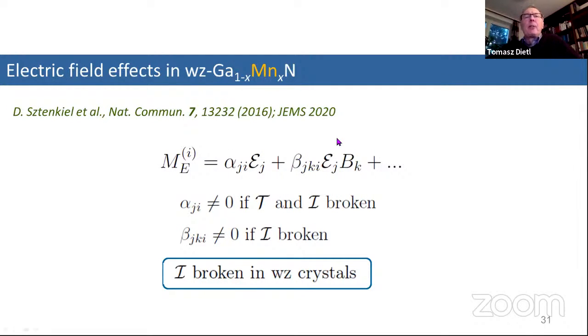And then this is non-zero if inversion symmetry is broken. Why is it so? It's very easy to see that magnetization is an axial vector, electric field is a polar vector. So to transform a polar vector into an axial vector, this should change sign if we change time and if we change R also. So it's very clear to see. And we know that inversion symmetry is broken in Wurtzite crystals. So actually we have a very nice physical situation to observe these magnetoelectric effects for free, because we have broken inversion symmetry from the beginning.